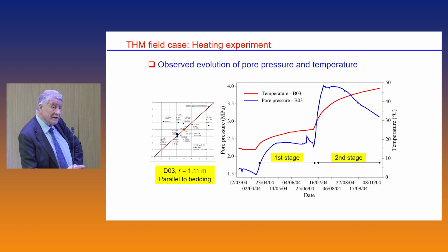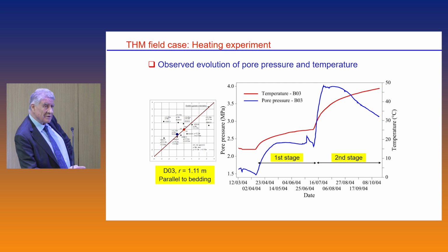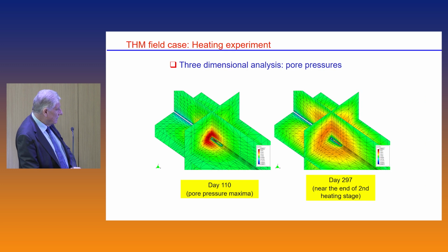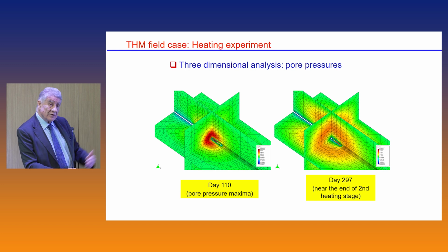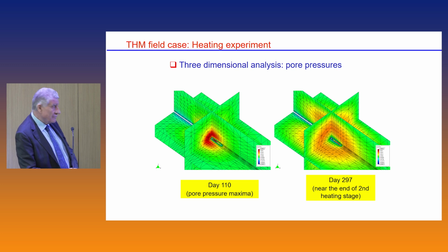4 megapascals is approximately what is reckoned, it's difficult to measure, but it's reckoned to be the minimum principal stress in Mont Terri. But it's also interesting that the temperature keeps rising, but the pore pressure reaches a maximum and then actually drops because of dissipation. The permeability is low, but it's not zero. These are some results. This is the pore pressure contours. I'm not showing temperature, which is not very interesting. The contours of pore pressures around the borehole, but as time goes on, you can see this maximum pore pressure actually, because of this dissipation, moves away from the borehole.